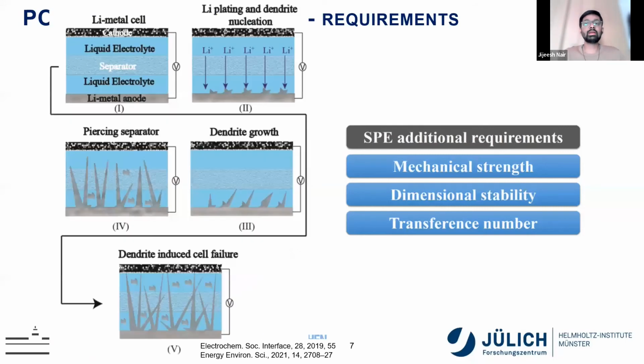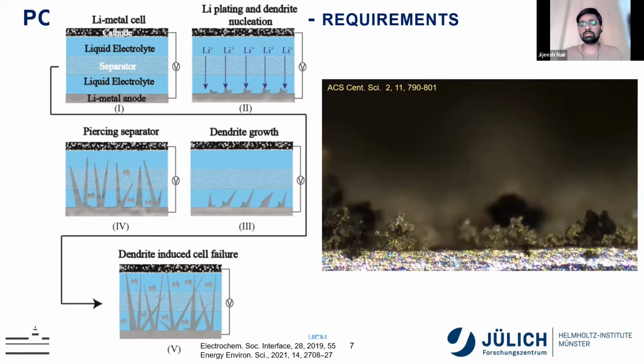And besides, the mechanical strength is one of the important parameters, because we are going to deal with the lithium metal, as also Professor Ruffo showed. If we are using liquid electrolyte in place of polymer, this can create dendrites. One of the reasons that we have to impart mechanical strength to a polymer membrane or other kind of solid state electrolyte is because we want to avoid dendritic growth and related short circuits. As you can see in this image, you can clearly see how high surface area lithium is deposited on the metallic surface. So this should be completely avoided, and this should be resisted for a safer battery.